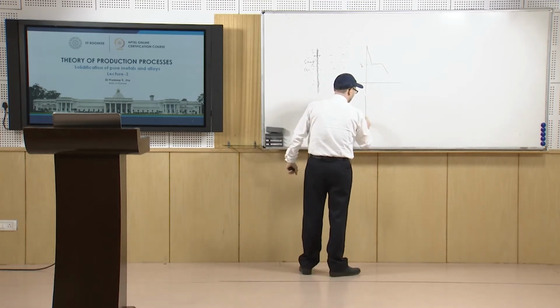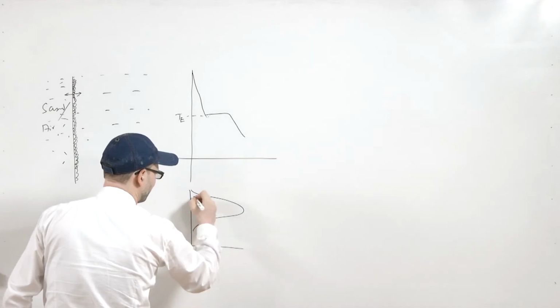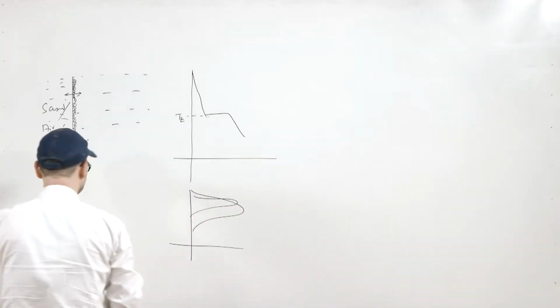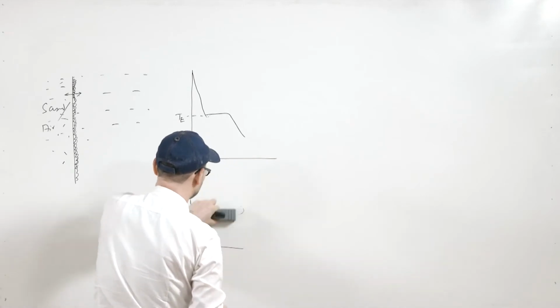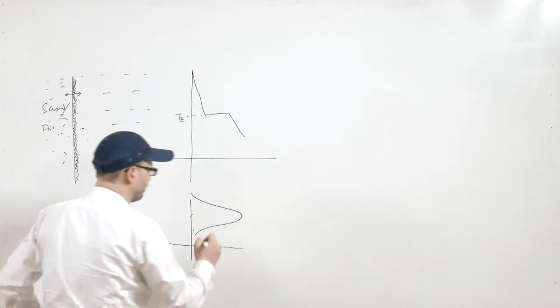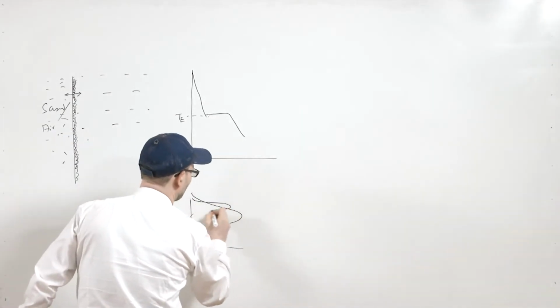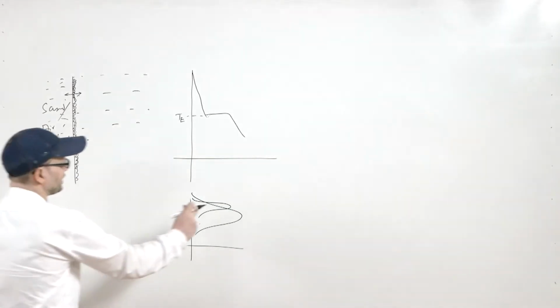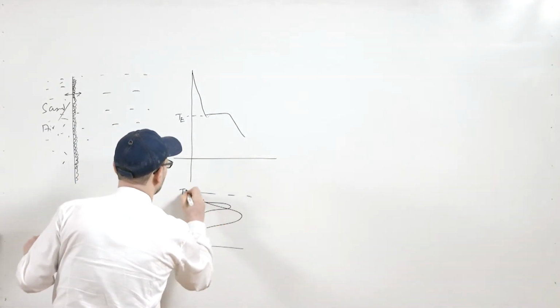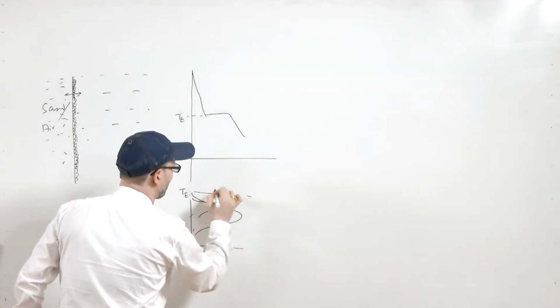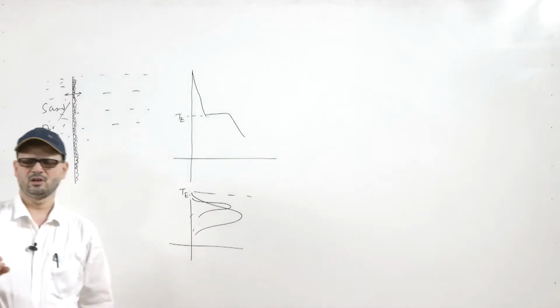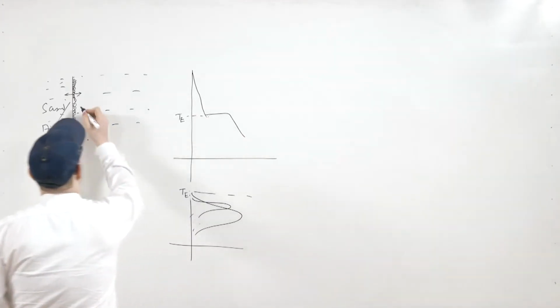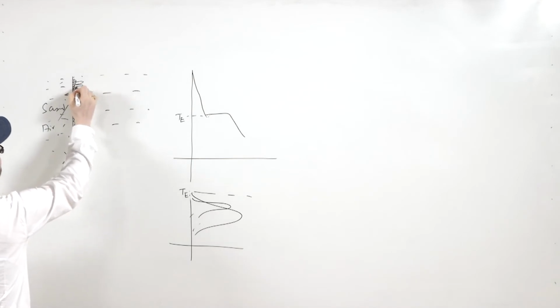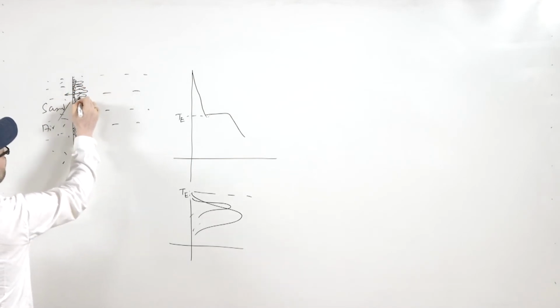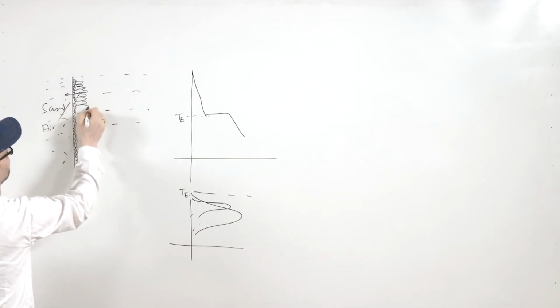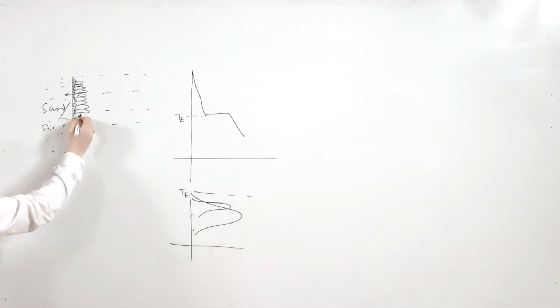and in fact in that temperature region the growth becomes predominant. We had seen earlier the rate of nucleation and rate of growth curves going like this. The rate of growth will be maximum towards this side. If this is the equilibrium temperature, the rate of growth is predominant when the temperature is a little higher, closer to the equilibrium temperature. That is why the growth of the grain starts. Now, the nucleation ceases and the growth of these grains starts.